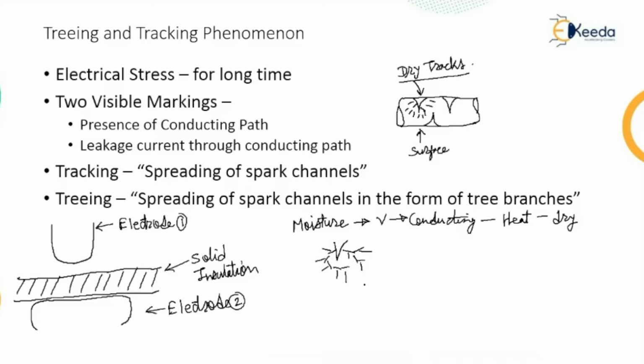Now, this is a cumulative process, and the insulation failure occurs when the carbonized tracks breach the distance between the electrodes. So when these cracks are formed and continuous between the electrodes, they can breach the gap between the two electrodes. When it gets breached, that becomes the reason for the formation of breakdown. So this is the cumulative process, as we said, and insulation failure occurs when the carbonized tracks breach the distance between the electrodes. This phenomenon is called tracking and is common between the layers of bakelite paper and similar kinds of dielectrics.